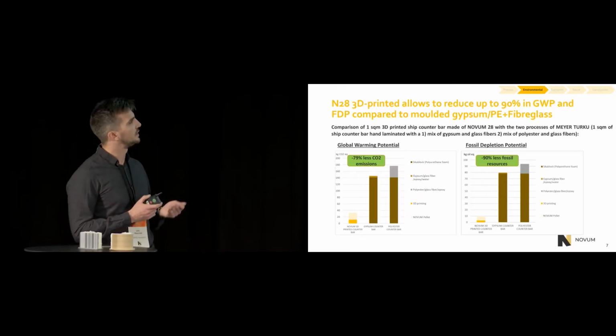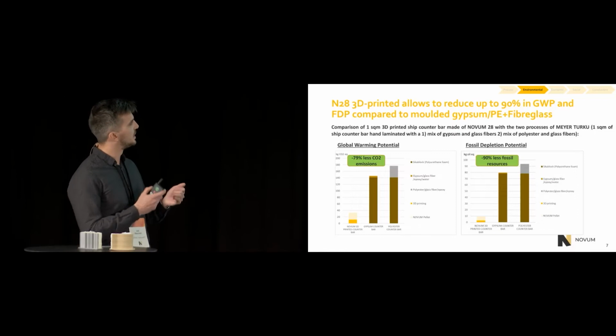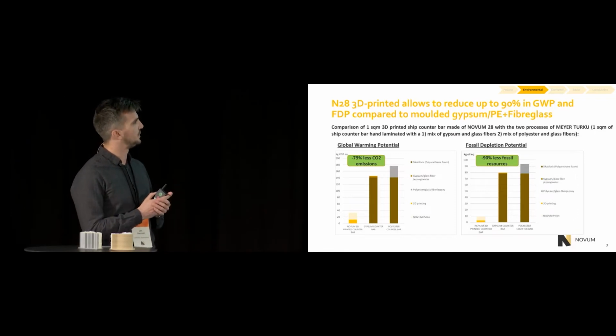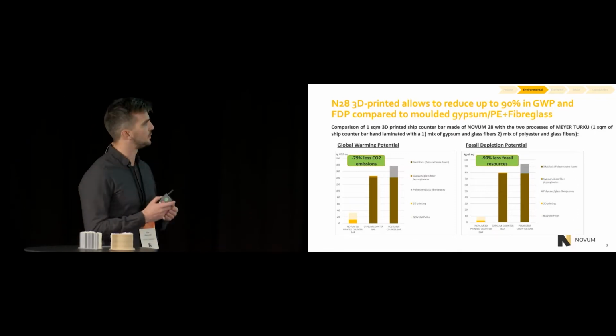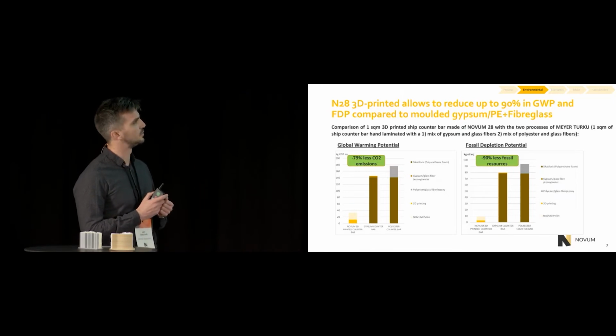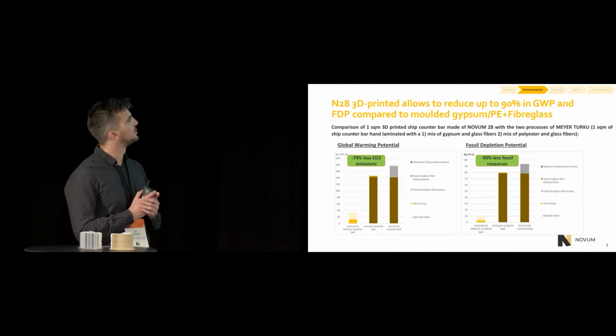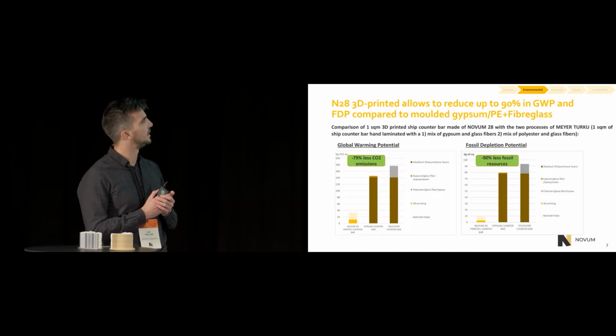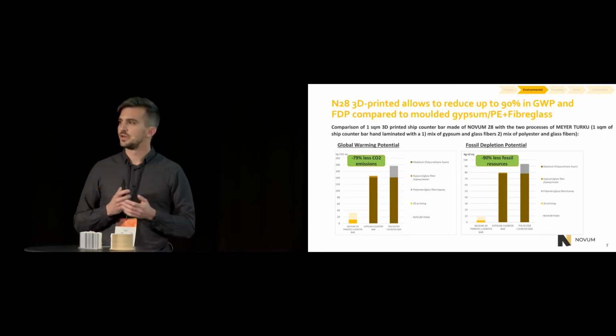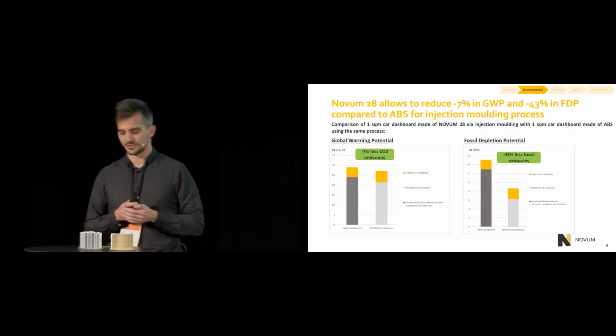And we can see that the figures speak for themselves. We have really good results concerning our process using 3D printing and cellulose-based material. We have a reduction of 79% in the CO2 emission and a reduction of 90% in fossil resources.